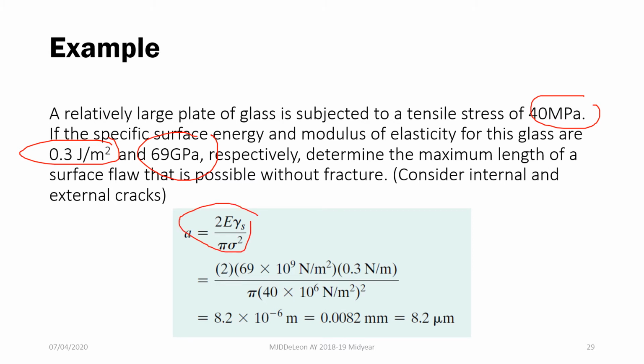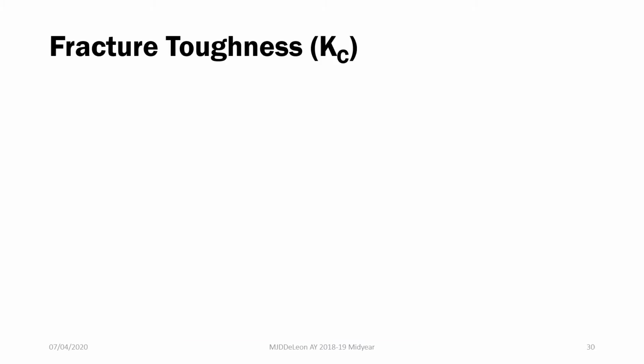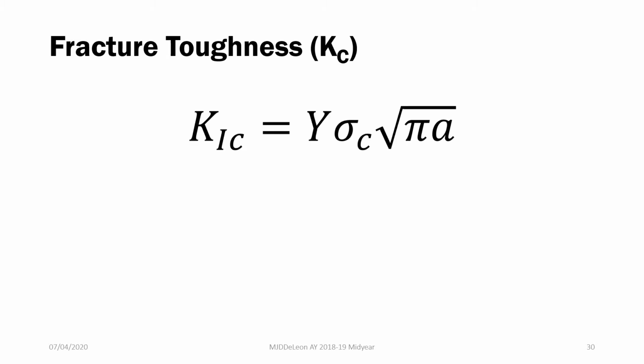Putting it in this equation, we would get 8.2 micrometers or 8.2 microns. Or makita natin, maliit na crack lang, pwede nang mag-fracture yung glass natin. So we have a parameter which we call your fracture toughness, Kc. In this, Kc is equal to y times sigma c times square root of pi a.